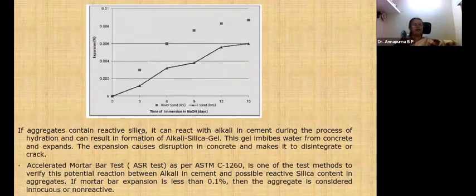This test we also call the accelerated mortar bar test, which we call the ASR test. It is one of the test methods where, according to the codal provision, the expansion should be less than 0.1%, then the aggregate is considered non-reactive. So here we can see that both the tests are less than 0.1%. Though it is less than 0.1%, the reaction on the M sand is less than the river sand.